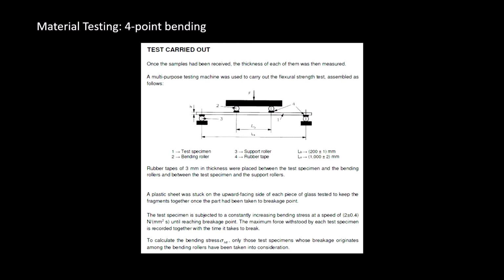4-point bending, per EN 1288-3, on 360 by 1100 millimeter samples with smooth ground edges. They were all fired flat in the slumping kiln with the same time, temperature, and duration that was expected for the final project laminated glass. The idea was to test how it related to typical flat glass. As expected, the carved glass was slightly weakened by the carving, with a larger reduction in strength when the carved surface was in tension, but it still performed structurally.